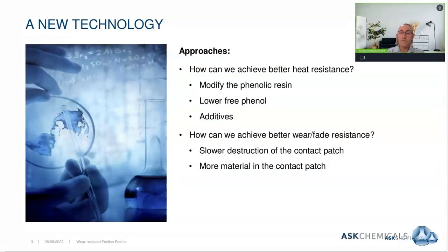So in practice, in the friction application, how does this interpret into wear or fade behavior? If one wants a better wear or fade resistance, the basic theory behind it is that you would want a slower degradation or slower destruction of the contact patch or transfer film, or tribofilm, as some people may call it. Or secondly, you may need to leave more material in the contact patch. So these are the normal two methods by which you can achieve better wear resistance.